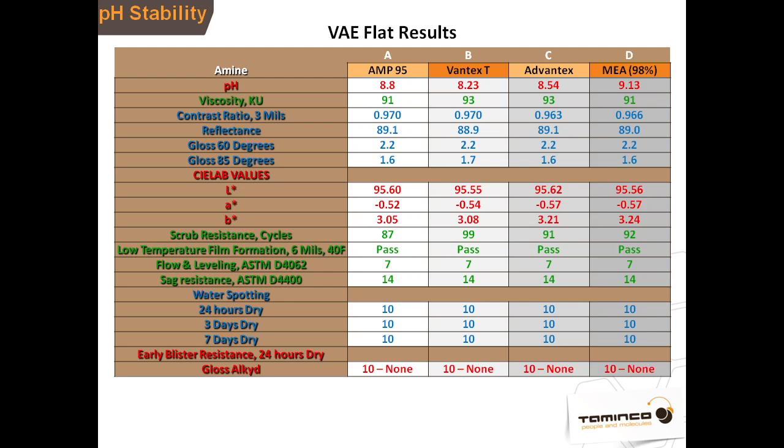I would suggest now that if you examine ladder studies with some of your additives relative to the more complicated additive, the alkanolamine as we're speaking of today, you're going to be able to reduce some of those other additive levels, because you're going to find that your paint has suddenly become over-dispersed and over-coalesced. And in some cases, that over-coalescence or over-dispersancy may degrade the performance of the paint. So you may find that by reducing some other levels, the paint performance improves. But I think this case is far more typical. You're not really going to have anything jumping out at you showing you that the paint is over-dispersed, and you'll have to find that through a ladder study.